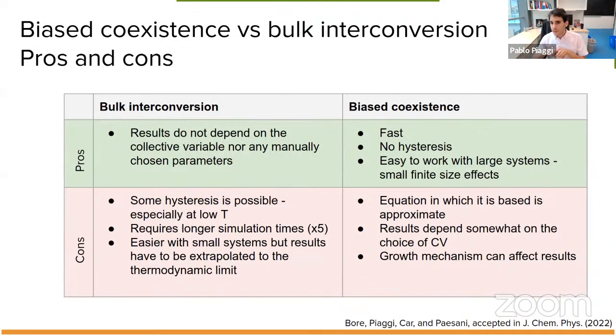So both techniques have their merits. I made a sort of a list of the things that I think are good from each one. I think they're both very useful to obtain the difference in chemical potentials between two phases. Perhaps the biased coexistence one is simpler in its application. So it's fast. I've never seen hysteresis in the collective variables. It is easy to work even with large systems, so you have very small finite size effects. Perhaps the limitation is that the equation on which it is based is approximate. This is not true for the bulk interconversion, for which the equations that I showed at the beginning of this talk are valid. Those equations are exact.